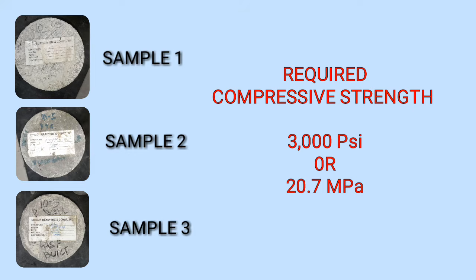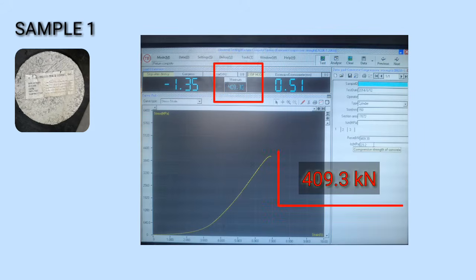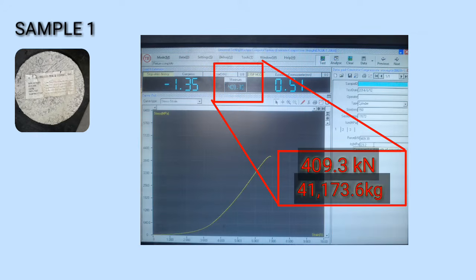Sample 1, sample 2, sample 3 with same sizes and strength specification. So let's see kung may variation sa strength nito at aabot ba ito sa maximum strength na kailangan natin, which is 3000 PSI or 20.7 megapascal. Sample number 1, based on the machine reading, meron itong 409.3 kN or equivalent value in kilogram na 41,173.6 kg. Ang bigat na binuhat ng sample number 1 natin.